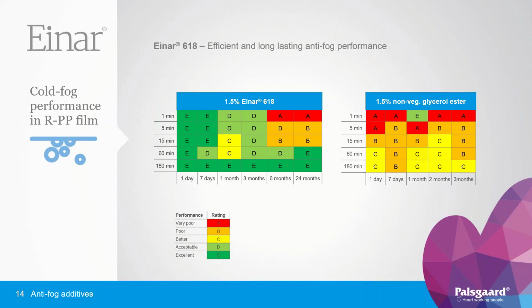And the reason for it is not because the polarity of the molecule has changed, it's simply because polypropylene is a polymer with higher crystallinity, and as these additives migrate in the amorphous phase, it's much more difficult to migrate in a polypropylene polymer, and therefore to get the necessary amount of additive on the surface, you will need more additive, higher loadings in the polymer to achieve your result. And even then, it becomes challenging on the surface, as results are indicating.